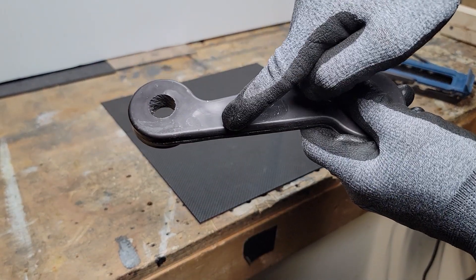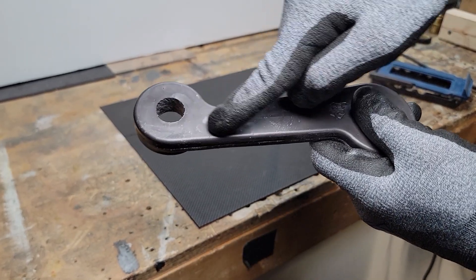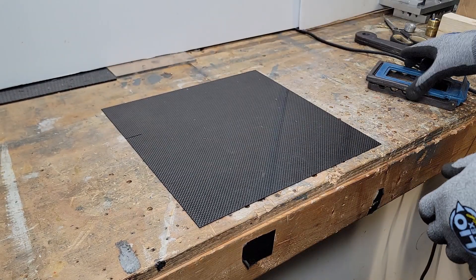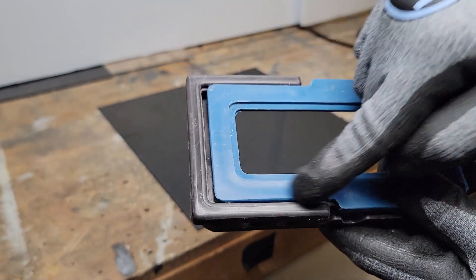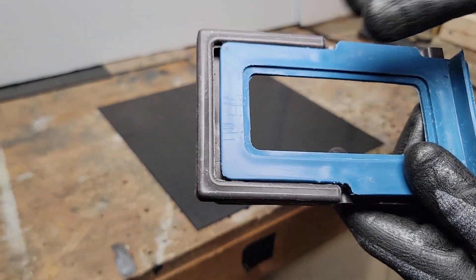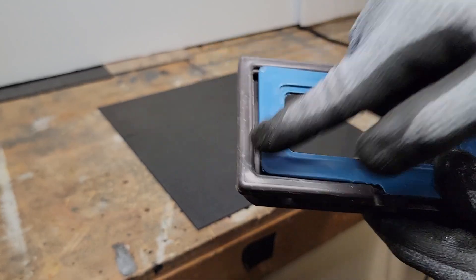After releasing the parts from the mold, a closer inspection of the finish reveals that some sections of the flat surfaces slightly deform after cooling. I suspect that this might be solved by preheating the mold more, or modifying the feature design — I'm yet to find out.